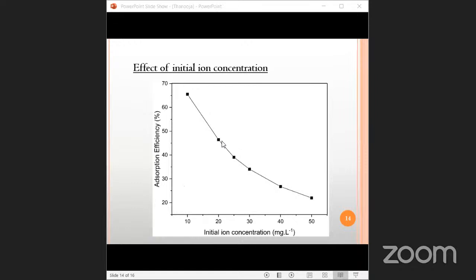Now, the effect of initial ion concentration. The variation of adsorption efficiency with change in initial ion concentration was studied at concentrations from 10 to 50 ppm. Adsorption efficiency was observed to decrease continuously with increase in initial ion concentration, and this can be due to the decrease in number of active sites on the adsorbent surface at higher initial concentration and increase in the number of ions competing for the available binding sites.